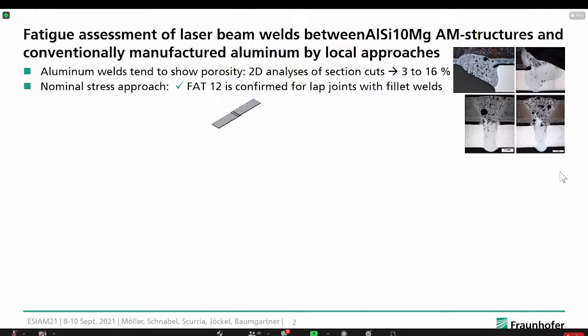Yeah, we did a little study on this, trying to decrease the large pores and the porosity in this area by preparation of the sheets in advance of welding, by etching and mechanical removal, in order to get rid of the oxides which might come from the outside. But obviously this was not the main reason why we see this porosity. From our point of view, the reason has to be inside the AM material, so we think the porosity which already exists in the AM material, due to the additional heat input, causes an extension of pores and porosity.